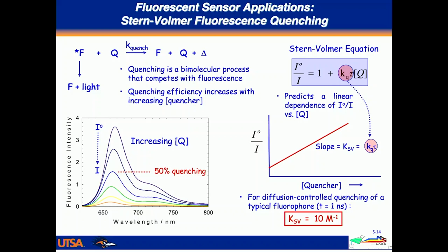There's a famous analysis of this type of experiment, called the Stern-Volmer analysis or the Stern-Volmer equation. The equation is written here, but mainly what I'm going to have you look at is that the y component is the fluorescence intensity divided by the quenched intensity, so it's called I0 over I. We make a plot of that inverse intensity versus the amount of quencher added. The reason we plot it this way is that Stern-Volmer predicts this should be a straight line. And the slope of the line is called the quenching constant, KSV.